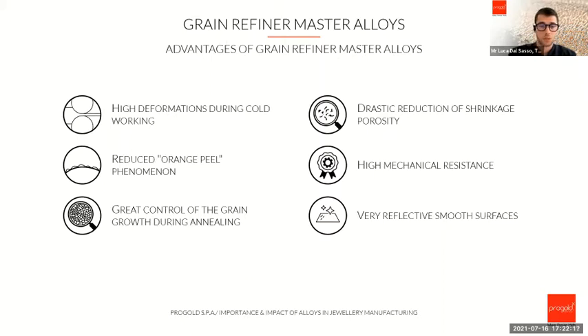The shrinkage porosity reduction is something we will go deeper into later, because we will see that there's a completely different porosity on fine grain alloys, which is less deep and uniform on the surface, so easier to remove. We will have less metal to remove in order to eliminate the defect. And the last one is the high mechanical resistance.